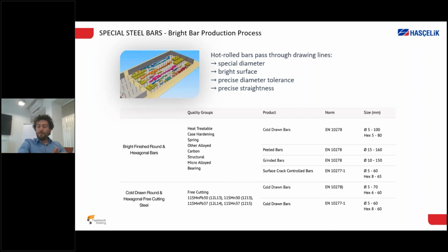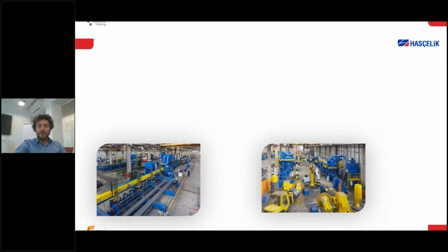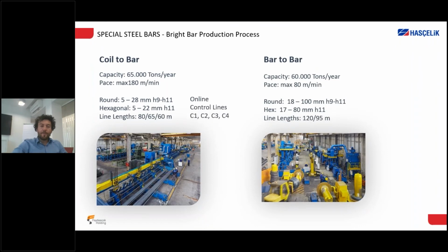So there are different types of production of bright steel bars. One is cold rolling, one is peeling, and one is grinding. So we have two lines from coil to bar. We supply coil from different sources, and we have a capacity of 65,000 tons per year for small sizes. We produce in these two lines from 5 millimeters up to 28 millimeters, and we can guarantee up to H9 tolerance. And bar to bar lines, we have two lines as well, originating from Europe, with a capacity of 60,000 tons per year. And we can produce here from 18 up to 100 millimeters, and tolerance up to H9.